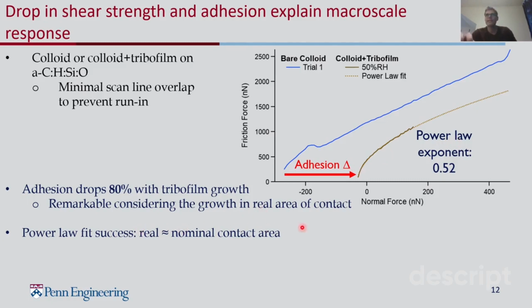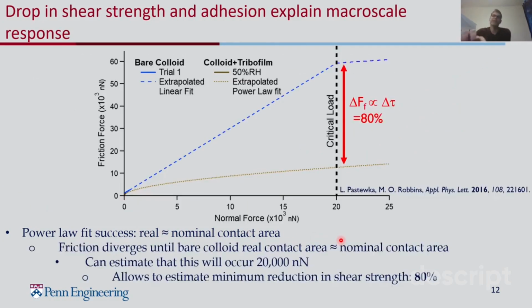Additionally, the fact that this is behaving like a single asperity contact means the real area of contact is approximately equal to the nominal area of contact. And that's useful to us in that there's one additional piece of analysis we can do, where we make use of this Robbins group paper from Johns Hopkins from 2016, where they did a theoretical analysis of a multi-asperity hemispherical contact. And they show that at some critical load, the linear scaling between the contact area and the normal load shifts over to Hertzian scaling, because all of these asperities are compressed to the point where the real area of contact becomes equivalent to the Hertzian case.